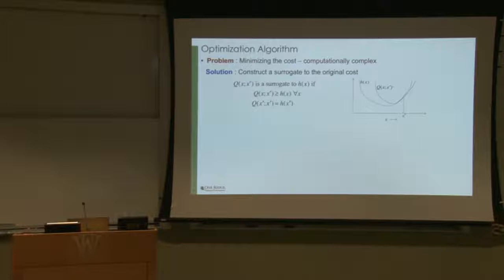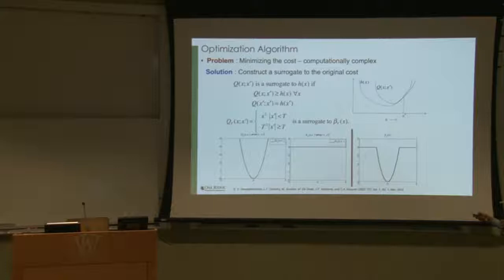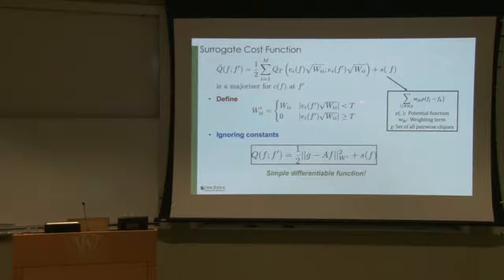To do that, we look at the penalty term itself, and so we had a penalty term which was like this. So we can show that we can build a surrogate function which is quadratic when the initial guess is inside the quadratic region, and it's a flat region when it's outside. So we can show that this is a surrogate function to the one term of the cost. And you can go ahead and replace every term in the cost function with this quadratic surrogate. And you get a new function that, if you minimize this, you'll guarantee you move to a lower value of the original cost.